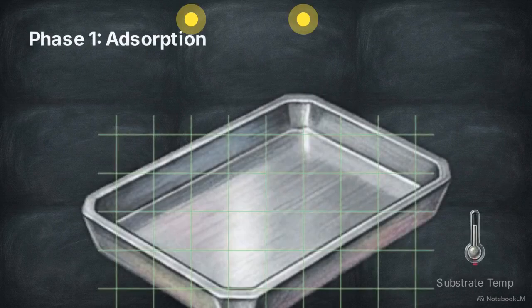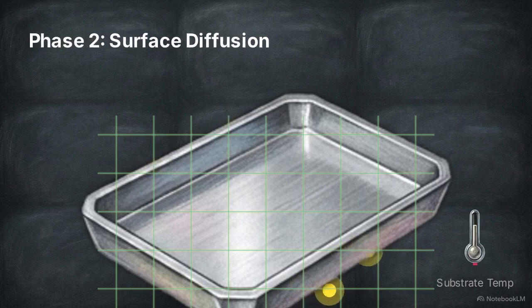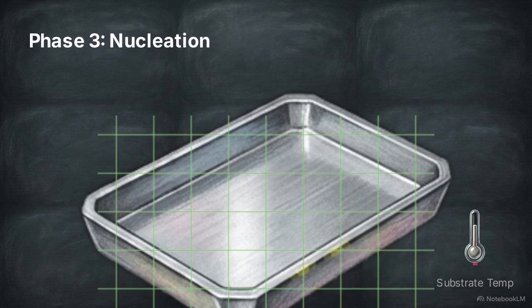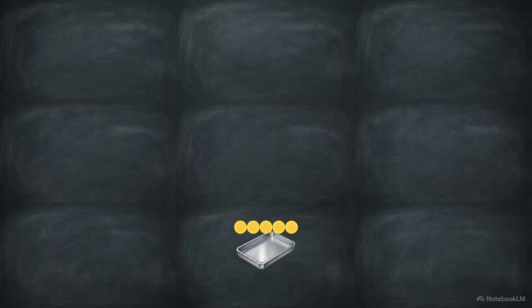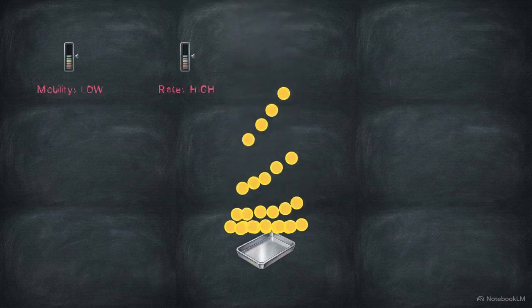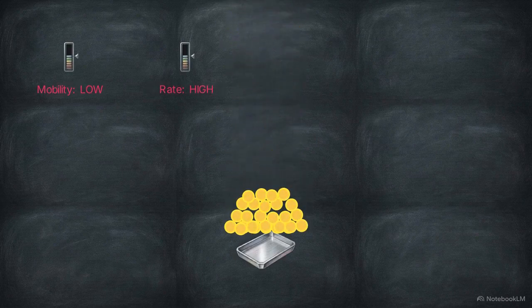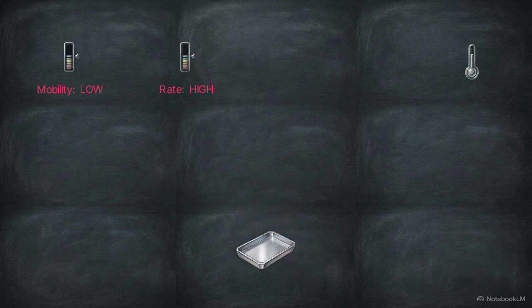When vaporized species reach the substrate, they stick and begin vibrating. This initiates nucleation through adsorption. These atoms then undergo surface diffusion, sliding across the substrate to find an optimal resting place before locking into position. The final position of these atoms is determined by the thermodynamic-kinetic balance. Thermodynamics drives the system to minimize surface energy, which encourages atoms to clump together. Kinetics acts as a barrier to that clumping. Variables like deposition rate, substrate temperature, and atomic mobility can prevent atoms from reaching their lowest energy state.